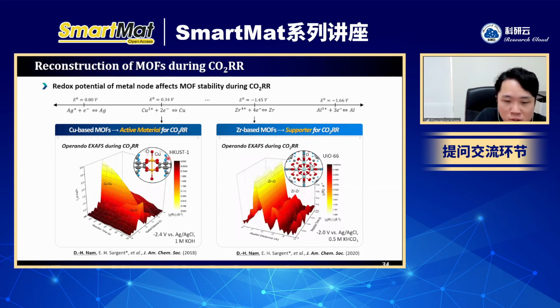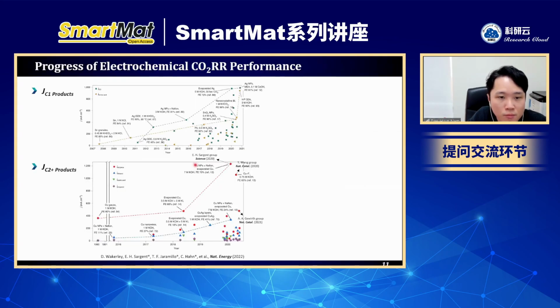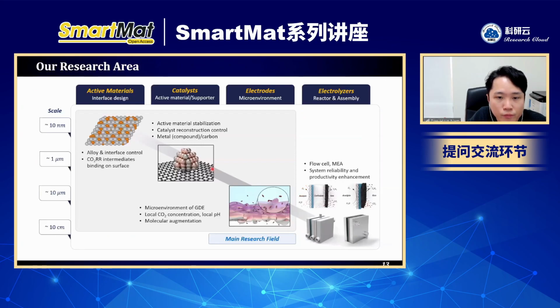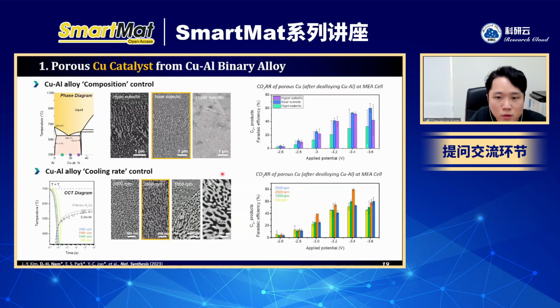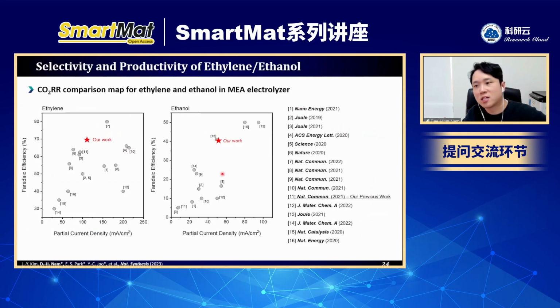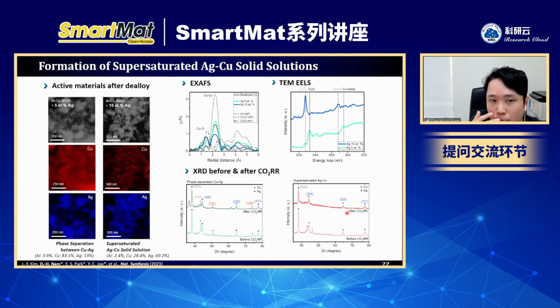This is not limited to HKUST-1. If we use copper porphyrin or copper phthalocyanine or another kind of organometallic complex, although copper starts from a single atom, it will be reduced to form copper clusters or copper nanoparticles. This kind of phenomenon can also be shown here. In the case of MOF, because copper starts from a single atom,